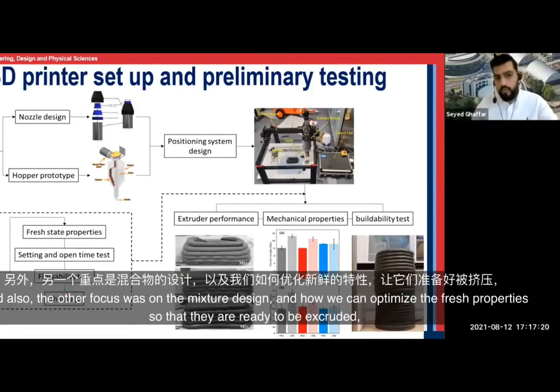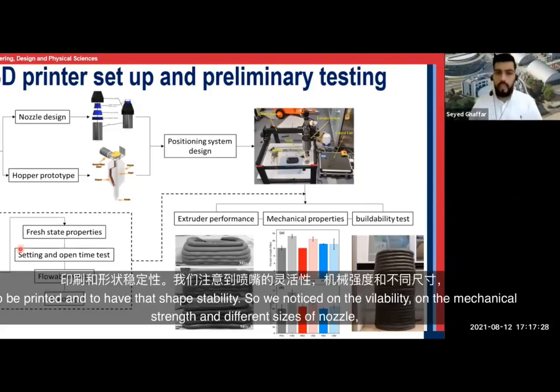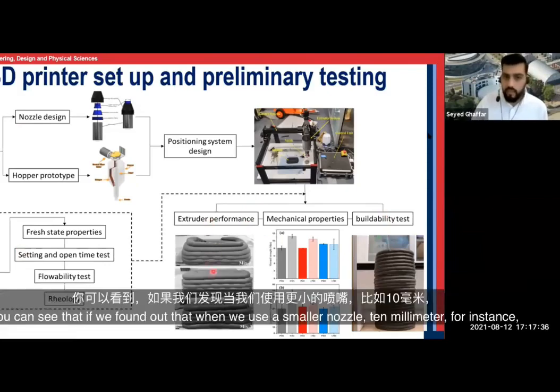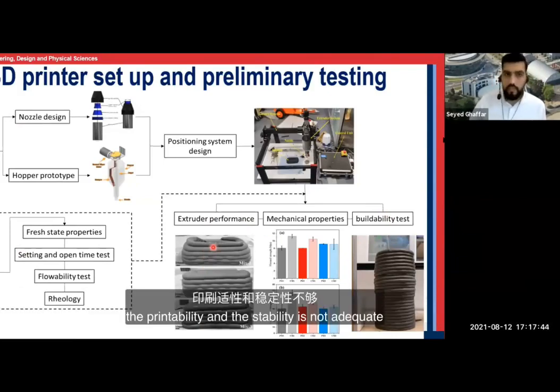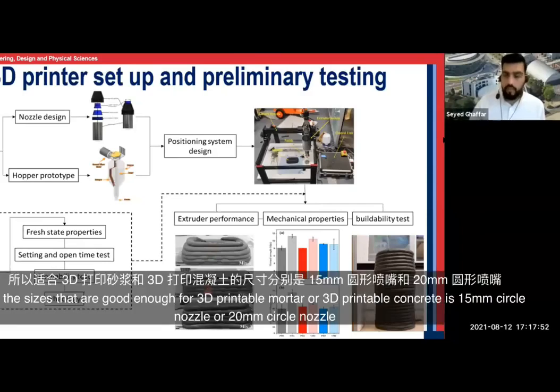The other focus was on the mixture design and how we can optimize the fresh properties so that they are ready to be extruded, to be printed, and to have that shape stability. So we did tests on the flowability, on the mechanical strength, and different sizes of nozzle. We found out that when we use a smaller nozzle, 10 millimeter for instance, the printability and extrudability is not adequate. So the sizes that are good enough for 3D printed mortar or 3D printed concrete are the 15 millimeter circular nozzle and the 20 millimeter circular nozzle.